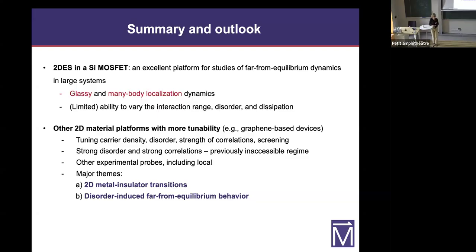You said you have fluctuation data. Is that also time resolved? Yeah, it's the same measurement, just a different protocol. You don't change the density, just cool the system down, measure conductivity as a function of time, and then you do statistical analysis. You look at the power spectra, fourth order statistics. Because you of course mentioned that the fluctuation dissipation relations will not apply.